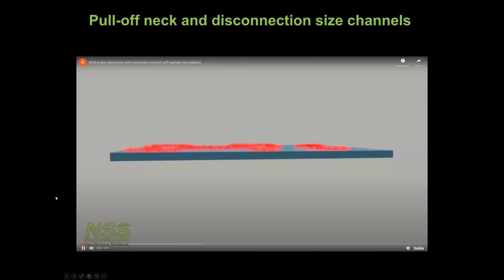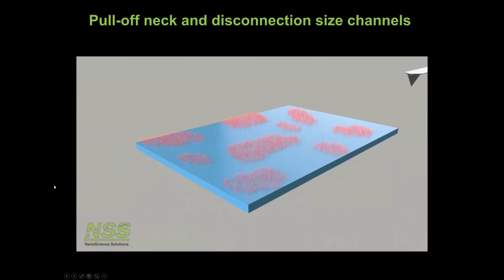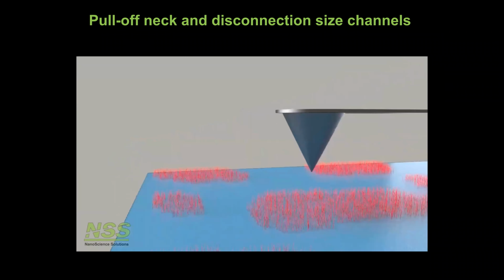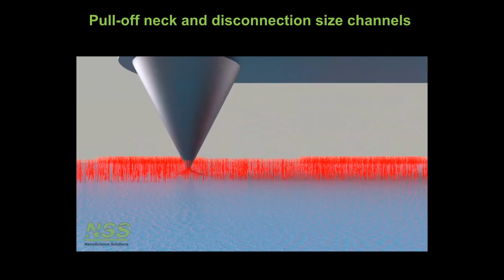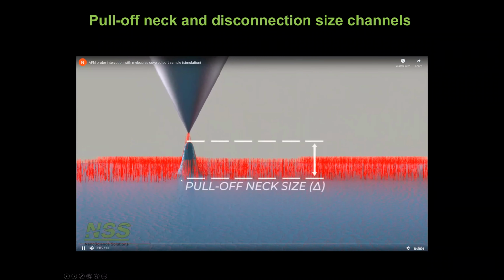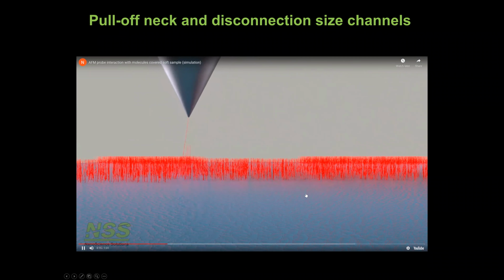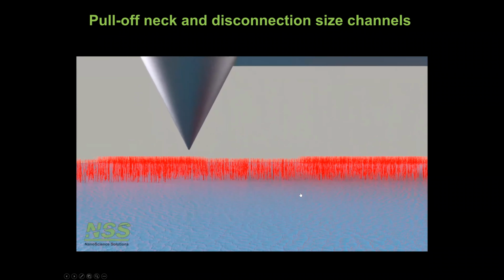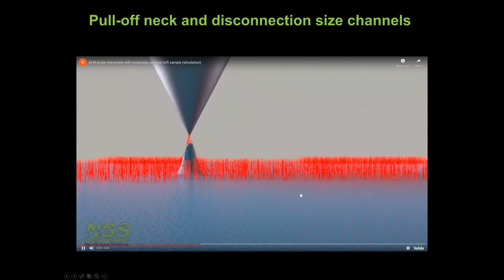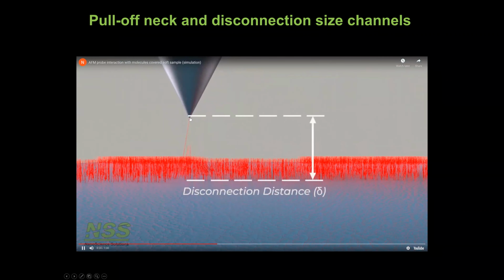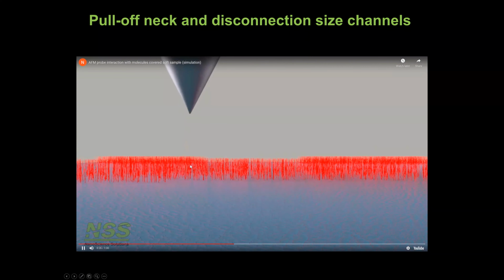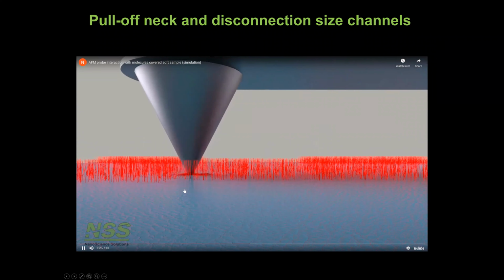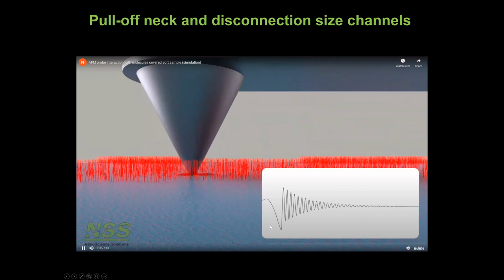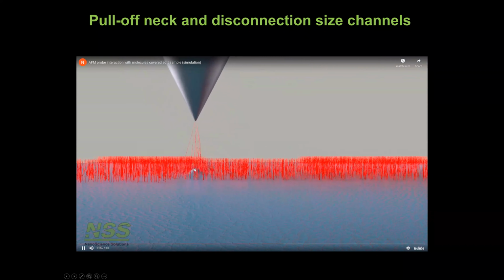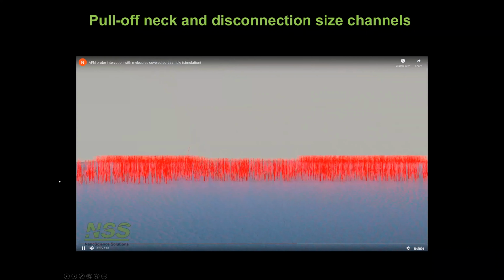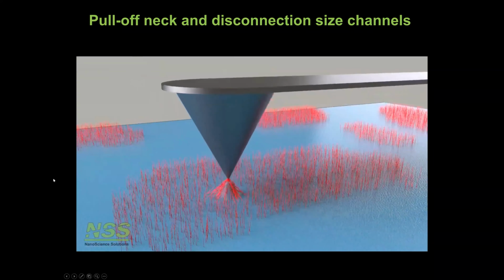To give you a feeling of the other two channels, which are really unique and interesting, look at these simulations. When the probe touches the surface, it develops some neck, the pull-off neck size. That's what we can measure using analysis of those force curves. We can even measure the disconnection distance, the size of the molecules which can be stretched by the probe, and do it at each touch. Well, that's the sound, like a ding, that's why we call it ringing mode. When the probe disconnects, it creates a ringing.